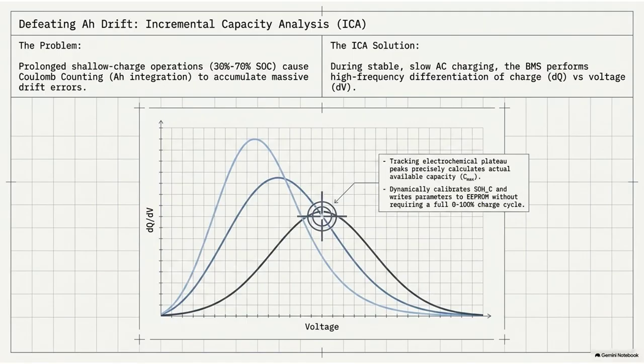Incremental Capacity Analysis, or ICA. Yes, ICA relies on high-frequency differential calculus, specifically analyzing the dQ/dV curve. That's the derivative of capacity with respect to voltage. Right. During a slow, stable AC charging session, the voltage of a lithium-ion cell does not increase in a perfectly straight line. The graphite anode undergoes distinct staging phase transitions as lithium intercalates into the layers. And these phase transitions create subtle plateaus in the charging curve, right? Where the battery absorbs a significant amount of charge capacity, the dQ, with almost zero change in voltage, the dV.